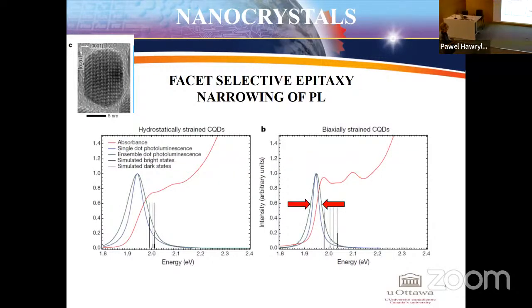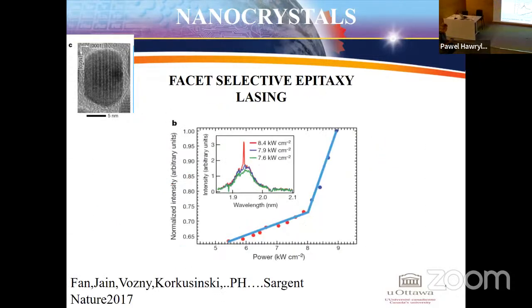And now we look at the hydrostatically strained, so in all directions equally, and you see a broad emission spectrum, and then when we biaxially strain, you see splitting of these levels and narrowing of the emission spectrum, because now we just have a single level to recombine. And if you pump the structure, you see nice lasing. So using some understanding at an atomistic level of these nanocrystals, we were able to overcome this limitation and demonstrate lasing of these nanocrystals.